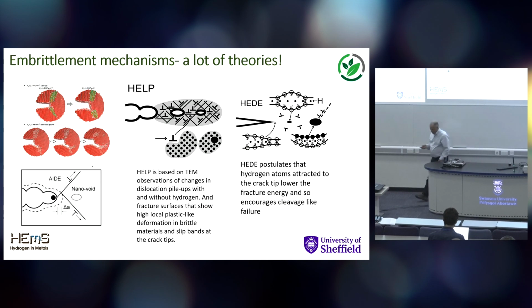Now, the theories of hydrogen embrittlement are numerous. People tend to start shouting at each other when they go through these different theories, because everybody sticks to one theory and it has to be right and the others all have to be wrong, don't they? Of course. But it's not quite like that, actually. But the famous ones are here. The HELP theory basically says dislocations run around, you get pile-up of dislocations, which leads to voids, and you get cracking from those. So that is suggesting that the dislocation mobility is much higher. I'll come back to that.